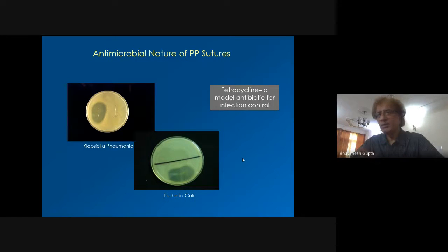And you can see over there how the antimicrobial suture works. You see the white there. In each petri dish, there are 2 samples. One is the white sample without any shadow. The other one is with shadow. Without shadow, the bacteria is growing in the petri dish. It's growing everywhere where the white filament is. But if you see this shadowed part, this modified suture, with the modified suture, there is a zone where there is no bacterial growth. So you can imagine that if you want to make medical textiles infection-resistant materials, this drug-modified suture doesn't allow bacteria to grow not only on the suture but also in the surrounding area, and this is how infection resistance matters a lot.